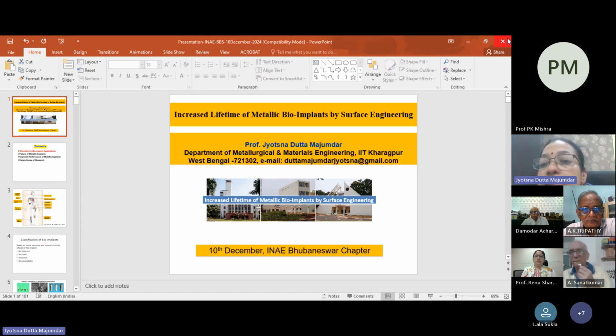Yes. So we cannot use it as processed condition. So we polished it mechanically, but it was not really much. So machining was not really too large. I mean, thickness was around 25-30 micron like that. 30 microns, okay. We also do nitriding to that extent only, 30 microns. We actually might do nitriding to a greater thickness and grind it down so that 30 microns is left, because if you leave it too thick, it will crack up when in action.